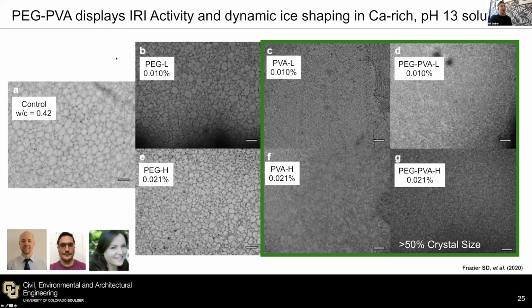So PEG-PVA displayed IRI activity, not showing the dynamic ice shaping, but it did that as well, in these really high, calcium-rich, pH 13 solutions. Over here on the left, we have a control sample after 30 minutes of incubation on the cold stage with no polymer dissolved in solution. And you can see the ice crystal grains are actually quite big. PEG alone at a low concentration and a high concentration didn't display this ice recrystallization inhibition, but PVA at low and high and PEG-PVA at low and high concentrations did. And it kept the crystal size more than 50% smaller than the blank, the control solution. So we were really excited about this.